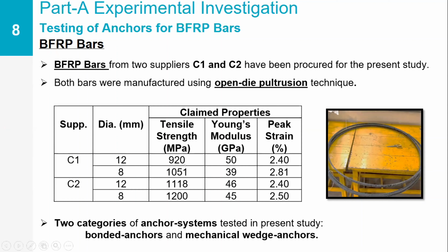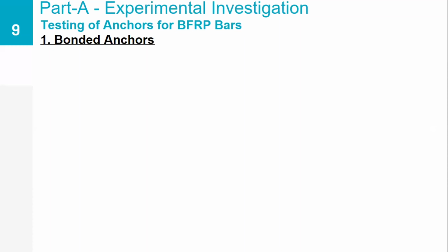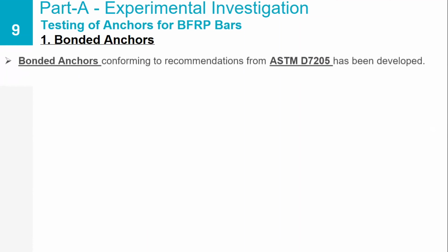So it ranges between 920 MPa and 1200 MPa for the tensile strength, and the Young's modulus for FRP is always lesser than the Young's modulus for steel. So it is somewhere between 40 to 50 GPa, and also the peak strain is somewhere between 2.5 to 2.8%. So as I said, the two types of anchor systems have been tested in the present study. One is the bonded anchor and the second one is the mechanical wedge anchors. So coming to the study on the bonded anchors.